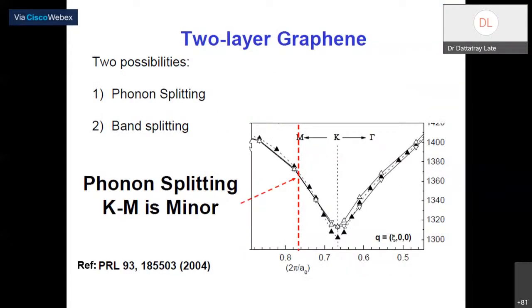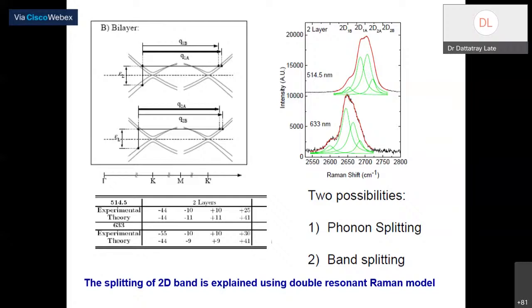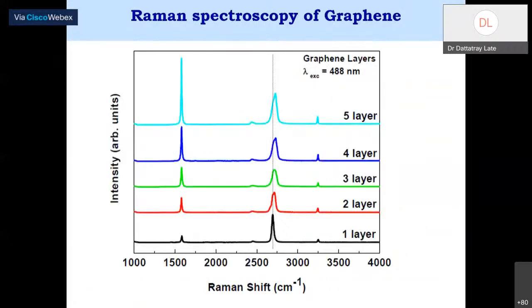There is a lot of physics, or chemistry, behind it, the basic reason why the spectra are distinguished. This can be described by phonon splitting and band splitting. The splitting is again explained using the double resonant Raman model. This double resonant model tells us that when we excite a phonon, it goes to a higher level state, and then once it is populated in the higher level state, it comes back to the ground level, and this gives two particular possibilities, which are known as phonon splitting and band splitting. So this is the brief about the double resonant Raman model. You can see here, once we have one layer, two layer, three layer, four layer, or five layers of graphene, how we can distinguish these particular bands.